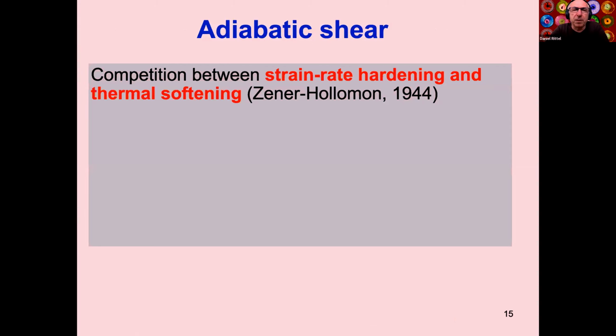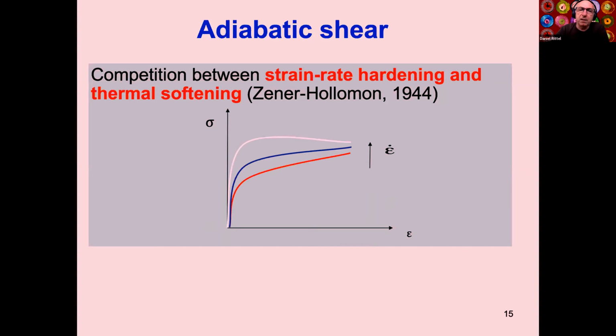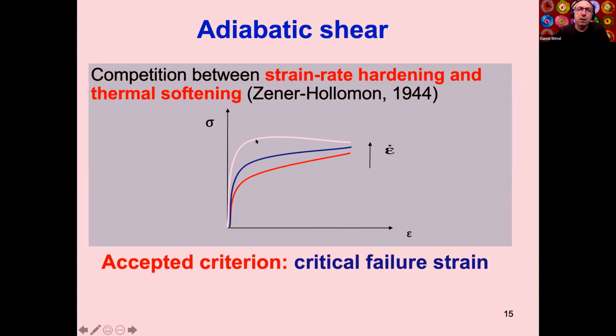So let's talk a little bit about the adiabatic shear. The conventional wisdom has it that strain rate hardening, that has been talked about quite a lot today, and thermal softening that has been evoked are in fact competing. And this is due to Zener and Hollomon, 1944. So if I plot a stress strain curve, that's what I get at low strain rate. I increase the strain rate, the material is harder or stronger, but its capacity to strain harden decreases. And eventually, if I increase the strain rate even more, the material is stronger, but then loses its hardening capacity, starts to soften, and becomes unstable in the sense of plastic deformation of materials. And when it becomes unstable, this is where you can expect a shear band to develop.